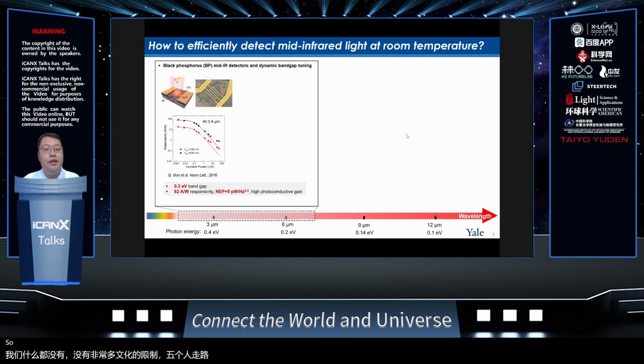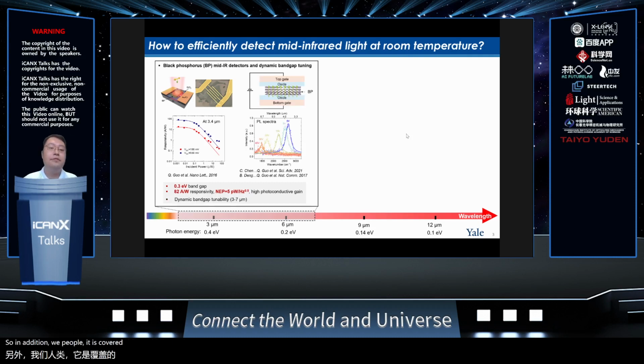In addition, we discovered something very interesting in black phosphorus. We found that by simply applying a vertical electric field across the black phosphorus, we can dynamically tune the band gap of black phosphorus, even to 7 micron. This can extend the spectral response of black phosphorus to even longer wavelengths, up to 7 micron.